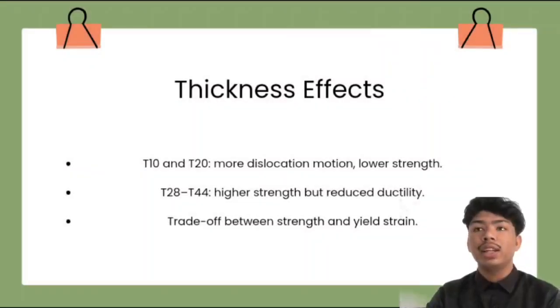In this part of the study, the effect of the magnesium aluminate layer thickness on mechanical behavior was investigated using the 5 interface models T10, T20, T28, T36 and T44, representing increasing ceramic thickness. The results show that T10 and T20, which have thinner magnesium aluminate layers, allow more dislocation motion across the interface. This leads to lower strength but higher ductility.